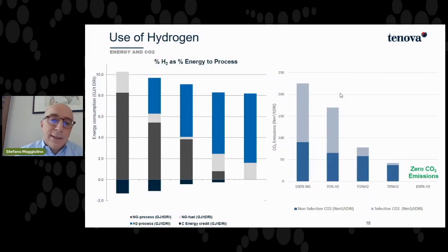Here we summarize the benefit of using hydrogen, both in terms of energy consumption and in terms of CO2 emissions. Here we can see in the first graph how the total energy used in the reduction process goes from above 10 gigajoule per ton to a range of 8 gigajoule per ton. And you can also see how we can basically achieve zero carbon and CO2 emissions by using increasing quantity of hydrogen.